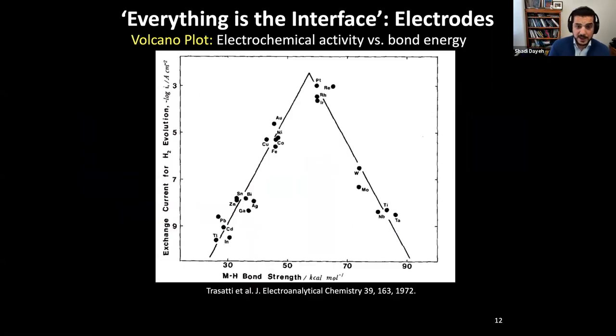So what makes a contact great for electrochemical sensing? This is what electrochemists call a volcano plot, where we're looking at the exchange current at equilibrium, as a function of the bond strength. Now, at low bond strength between the ion and the surface of the metal, which we are trying to use to sense how many ions we have in the medium, ions will come and adsorb and desorb very quickly. So they have small residence time on the surface.